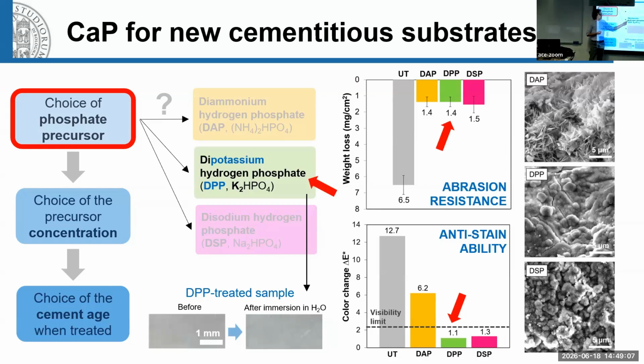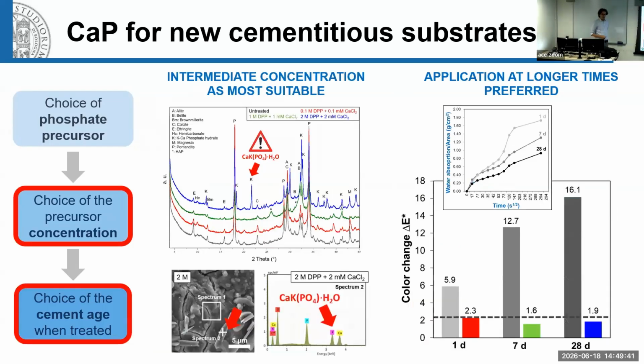Then we performed some performance tests in terms of resistance to abrasion and ability to prevent staining. So in the end, as you can see, DAP and the phosphates based on potassium and sodium all provided good results. In terms of anti-stainability, potassium and sodium provided even better results. So in the end, we selected the potassium phosphate as a good candidate for further tests.